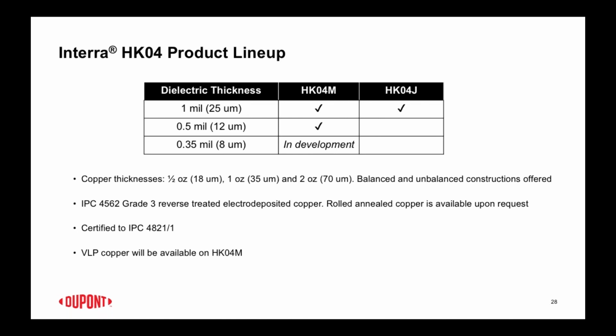The copper thicknesses are your typical thicknesses. For power and power distribution, you're typically using 1 and 2 ounce copper, but sometimes for whatever space concerns, you use thinner coppers like half ounce. So we also do unbalanced construction, and they're available in your typical panel sizes for making circuit boards. And we can do it with both electrodeposited copper foil, and we can also do it with rolled annealed copper, depending on what the customer wants.